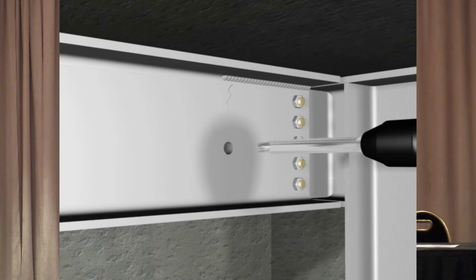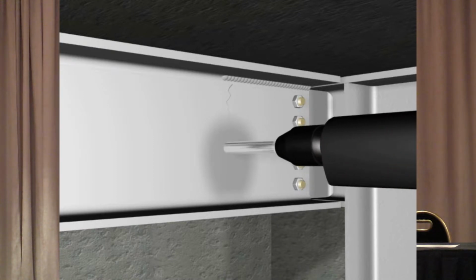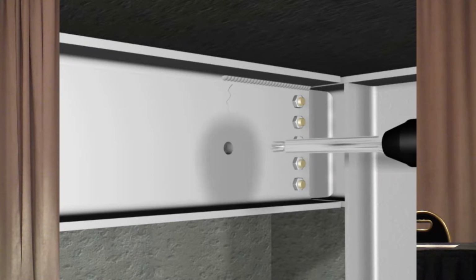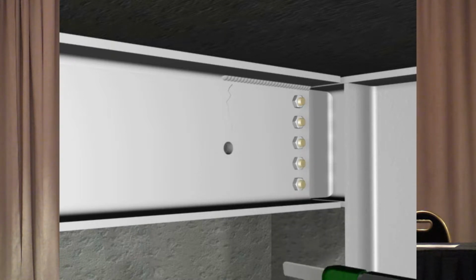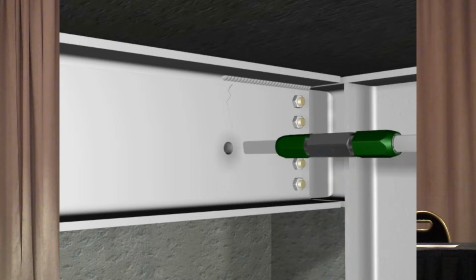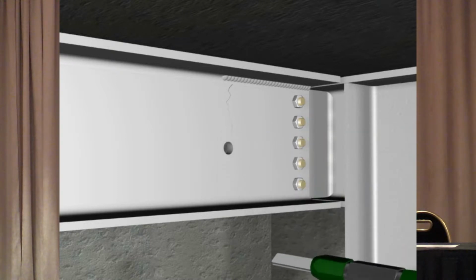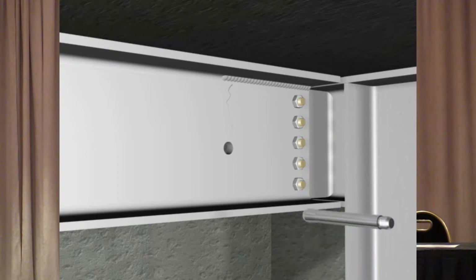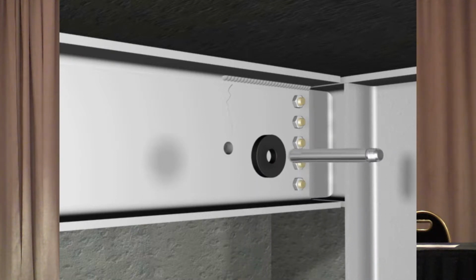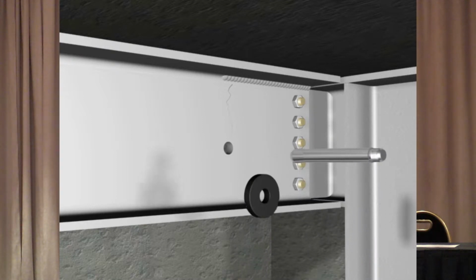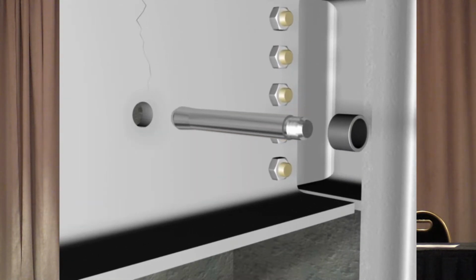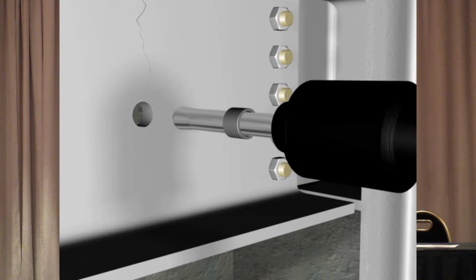That is so that when we actually use the hydraulic forces to impart the residual stress, if there's any micro cracking, we want to grow it into the mitigation area. It also gives you a little bit of a fudge factor in case you miss the crack tip, that you get that crack into that zone of compressive stress. Checking the mandrel for wear, sliding that sleeve onto the back. It's not split, so it can't go on the front, obviously. Putting it up to our structure.